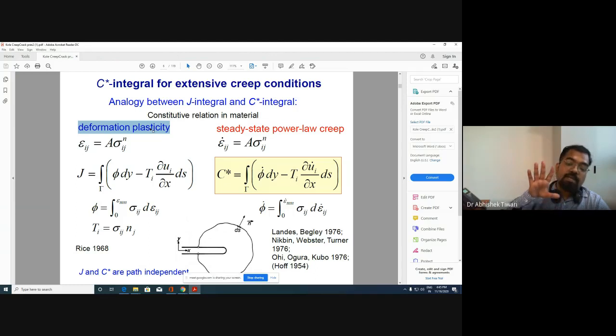You can assume it to be exactly equal to non-linear elasticity, okay? Because we are not unloading. And under those assumptions, the strain is a function of stress to the power something. We have discussed this kind of equation. So sigma is equal to K into epsilon to the power n, right? And if you reverse that equation, you will get this. If you write epsilon, then it will be epsilon is equal to 1 by K into sigma to the power 1 by n. That 1 by n is n here and 1 by K is A here, okay? So we have this kind of relationship between plastic strain and stress.